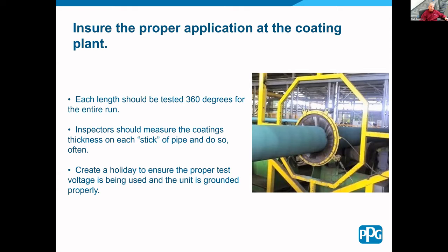We had a case one time, real quick story, where we went out to a job that an inspector shut down, and that inspector didn't even have a dry film thickness gauge in their possession. And we found out instead of 30 mils of coating, testing at 3,000 volts, they actually had 90 mils of coating, which would have been a 9,000 volt test, and the arc wasn't big enough in the holiday detector to bridge that air gap. That's why we tell you, make sure that you check, and check in multiple locations on the surface to ensure that you have the proper mil thickness and then proper voltage applied to address that mil thickness.